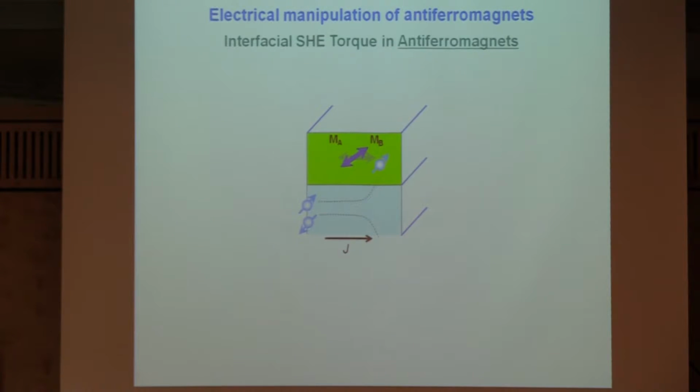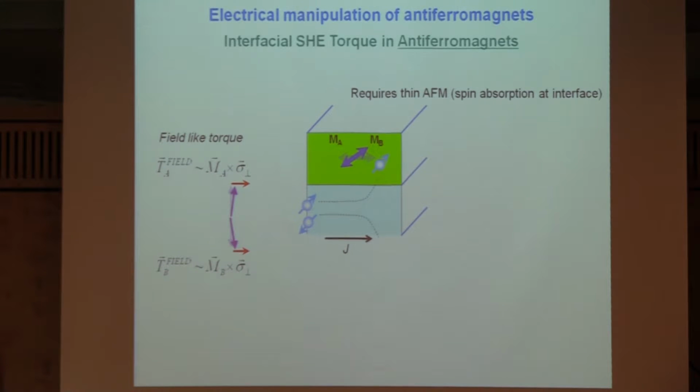So this is in principle the idea of people thinking you could use the spin Hall effect as a kind of effective spin injector into also antiferromagnetic systems where the spin accumulation at this interface diffuses inside. And from ferromagnetic spintronics, we know that there are two kind of extreme cases of torques which appear, which have a certain symmetry. One is the so-called field-like term.